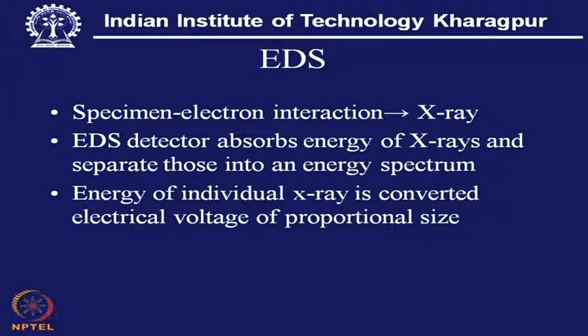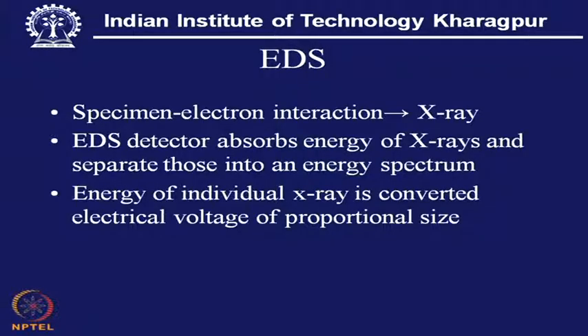Now, we have EDS, that is energy dispersive spectroscopy. In this case it is also X-ray, but it is no more the wavelength, it is the energy. The EDS detector absorbs the energy of the X-ray and separates it into an energy spectrum. That means the energy released as X-ray will be absorbed, and there will be a spectrum, and this spectrum is typical of all the elements present there, separating those.